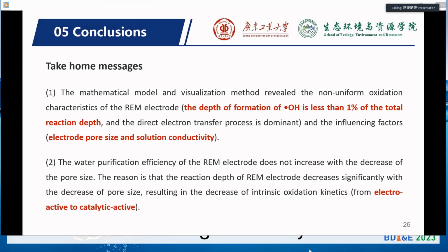So with regard to the electrochemical separation and purification technologies based on periodic reactions, we developed the mathematical model and the visualization methods to reveal the non-uniform oxidation characteristics of the REM electrode, and we found the depth for the formation of hydroxyl radical is less than 1% of the total reaction depth, and the direct electron transfer process is a dominant process, and the most significant influencing factors we found are the pore size and solution conductivity, because for a certain kind of water solution, the conductivity is determined.